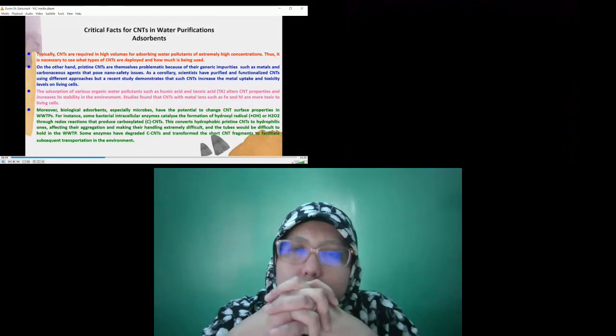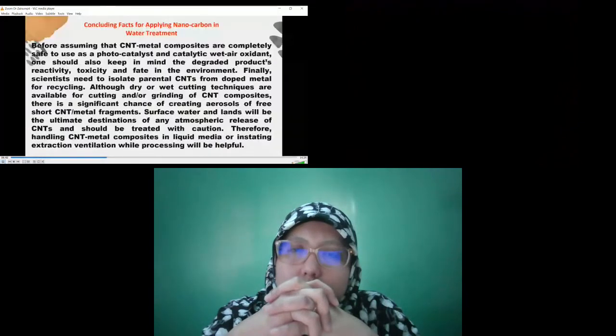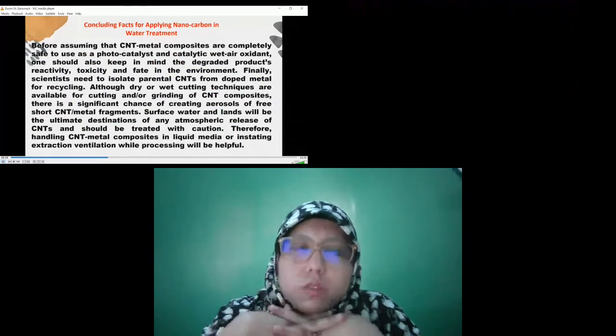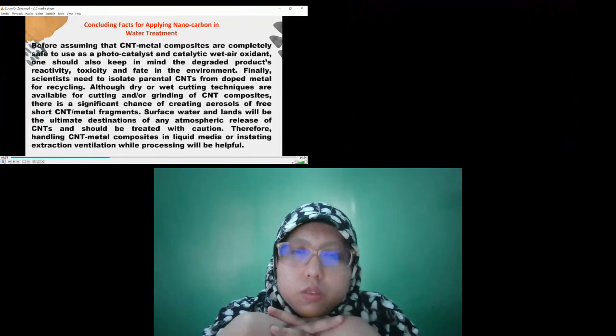CNTs or graphene can be used for nanomembrane synthesis, photocatalysts, or the catalytic wet air oxidation process for water treatment. In membranes, when nanocarbon is used, they can resist the biofouling process because they will destroy the bacterial cell. It is a very efficient photocatalyst, and it is very good for catalytic wet air oxidation also. But in both cases we have to consider the toxicity of the end product, because some degraded compounds will be present in water.